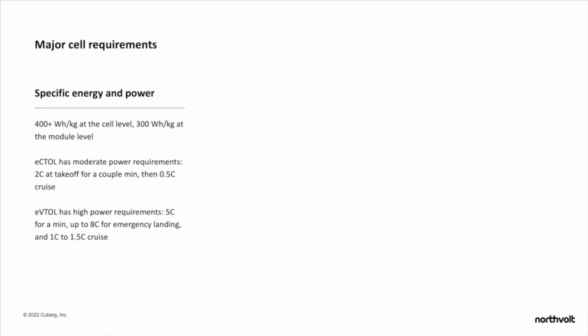eVTOL, because of the vertical takeoff nature, has much higher power requirements. I would say eVTOL is a much more diverse set of aircraft designs, so there isn't a one size fits all set of numbers for what eVTOL requires. But roughly speaking, probably on the order of 4 or 5C for 60 to 90 seconds for takeoff. And then sometimes you actually need to pulse up to 8C for 1 to 2 minutes for emergency landings, which I'll talk a little bit more later about why that's needed. But this is part of having redundancy in aircraft. Even if you have one entire module or pack go out of service, you still need to do an emergency landing. So very, very rigorous power requirements.